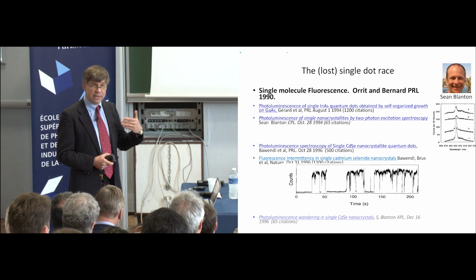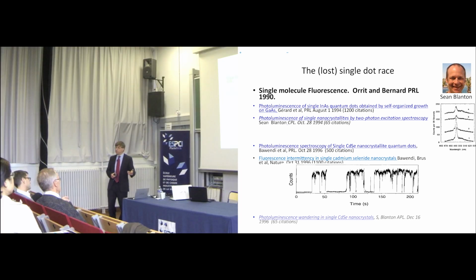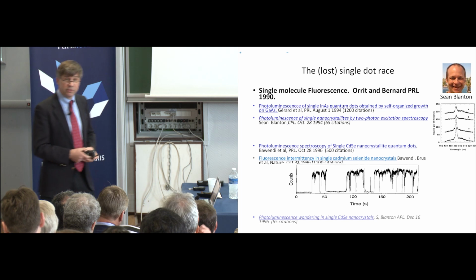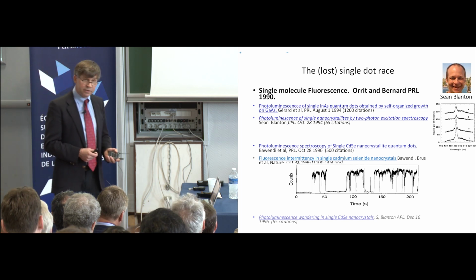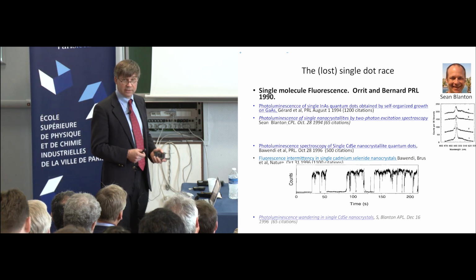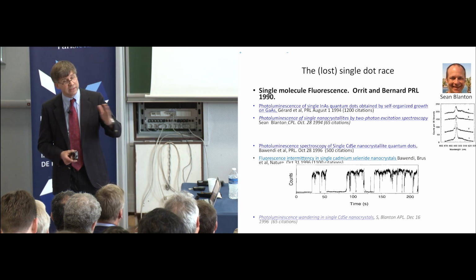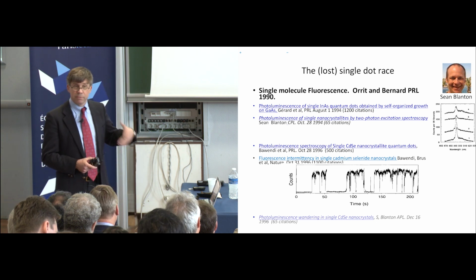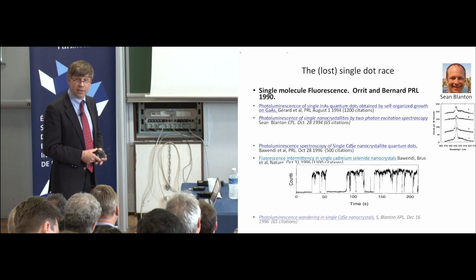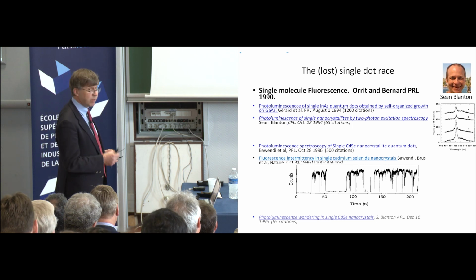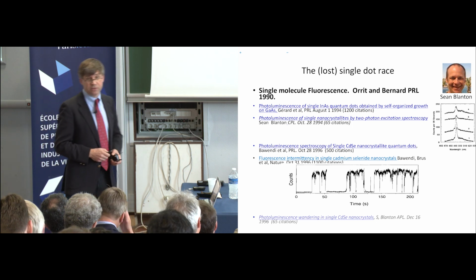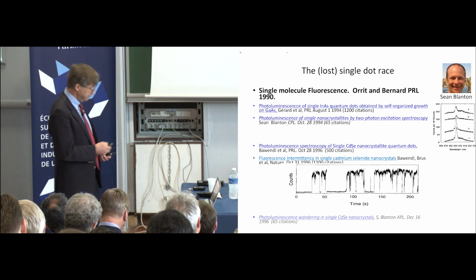So we didn't have to do any fancy piezo adjustments or mechanical adjustments of the focal position. We would always find a dot within about a micron cube in the sample. So it sounded really nice. And the other thing that I wanted to do with it was photoluminescence excitation spectroscopy just across the exciton line. And in principle, because it's 2-photon, you don't see the laser light, you only see the fluorescence. So you can do high-resolution spectroscopy right around the fluorescence line.